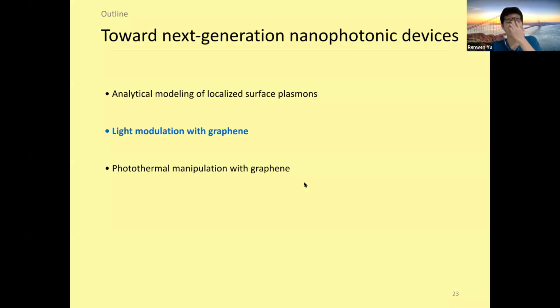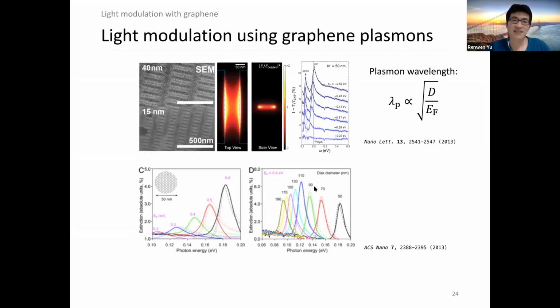So here comes the second part of my talk, which is light modulation with graphene. As I have mentioned, graphene plasmons are typically in the mid-infrared to terahertz frequency range. By nano-patterning graphene, from extended graphene to graphene nanostructures, it can support localized plasmons in this mid-infrared frequency range. Its plasmon wavelength is proportional to the lateral size of the nanostructure and inversely proportional to the doping level of graphene. So in order to push this plasmon resonance wavelength into the visible to near-infrared range, one needs to either greatly decrease the lateral size of graphene nanostructures or greatly increase the doping level of graphene. However, either way is technically challenging.